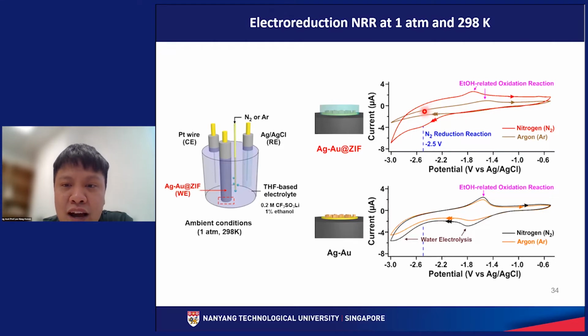So in this case, for the argon case, we note an oxidation peak over here. Okay, so this is related to ethanol oxidation reaction. After which, during the reverse scan, we see that there is no reductive peak in this region. However, in the presence of nitrogen bubbling, we also observe the anodic peak over here. But there is also an emergence of a new nitrogen reduction peak over here at around negative 2.5 volt.